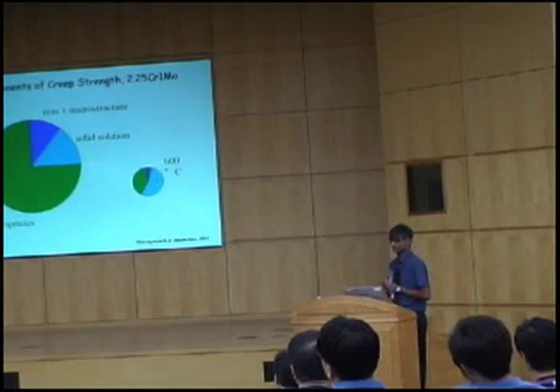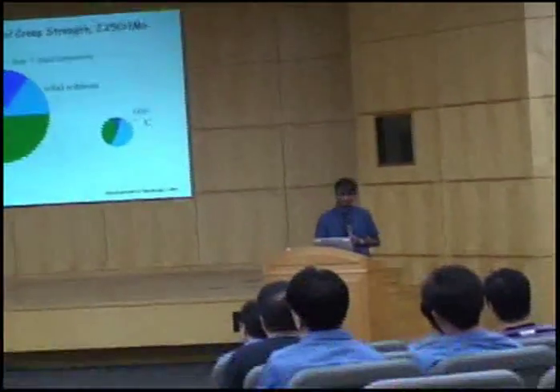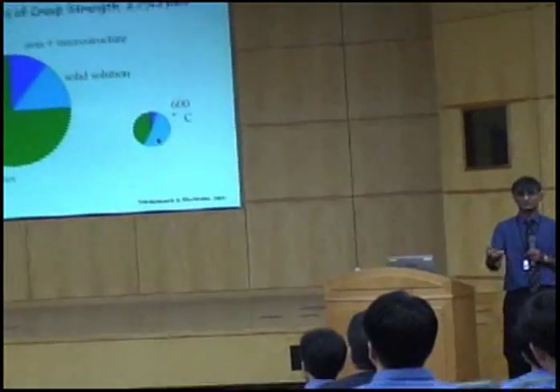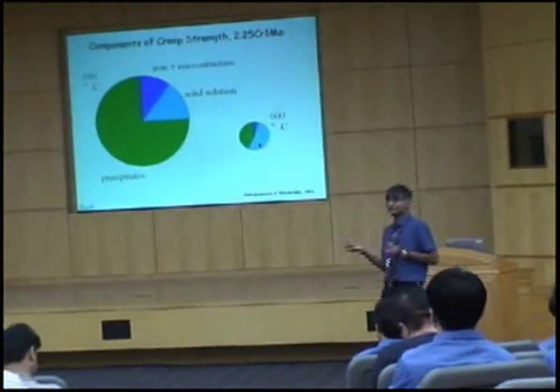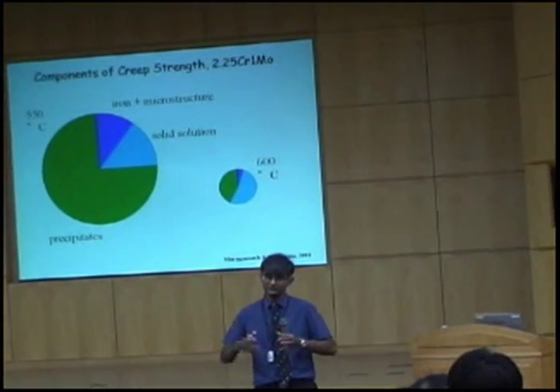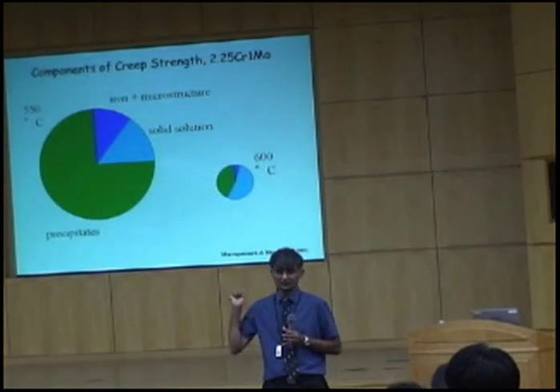But the thing that I want you to notice is the following, that at 550 degrees centigrade, the major contribution to strength comes from precipitates, molybdenum carbides and chromium carbides. As I go up in temperature, the precipitation hardening component decreases dramatically because of thermal activation. Dislocations can climb over precipitates. And the major contribution to strength really comes from solid solution strengthening, okay? Because that doesn't have any coarsening effects or anything like that. Solid solution strengthening is the most important at very high temperatures.